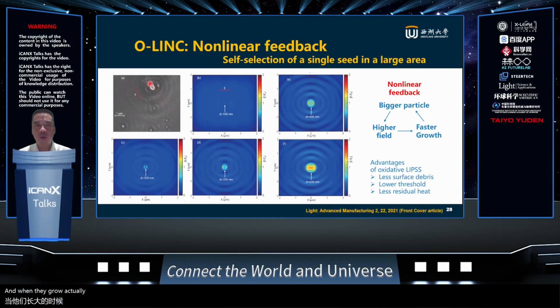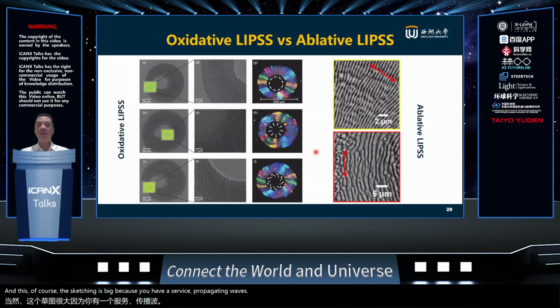When they grow, they grow in the same direction as the incident light polarization. So when the polarization is like this, the particle will grow up here and also here, so they will make a straight line. And then, as you can see from here, when they grow at this end, they also affect here and here. That means after a very long structure, you will also grow a small thin line here, here, and then here, here, here, here, growing. And then you will generate periodic structures. This is exactly similar to these laser-induced periodic surface structures. And of course, the scattering is because you have a surface propagating wave. And this is how we grow them.